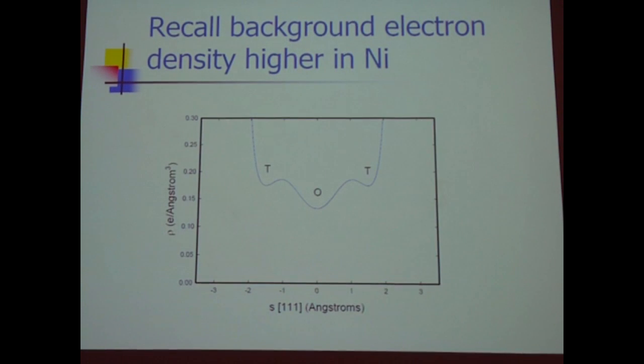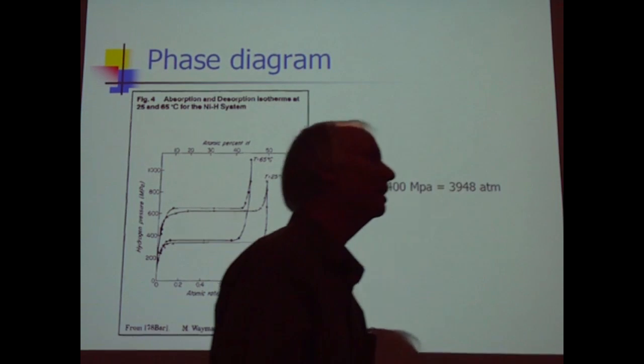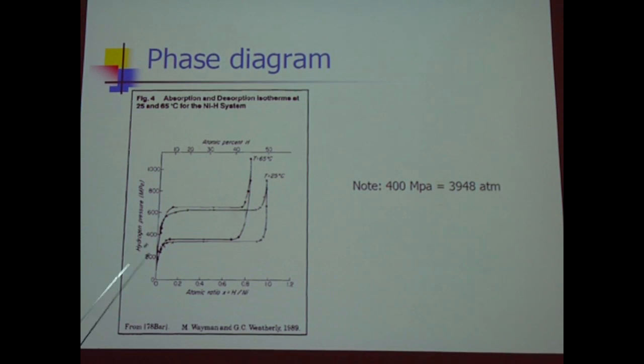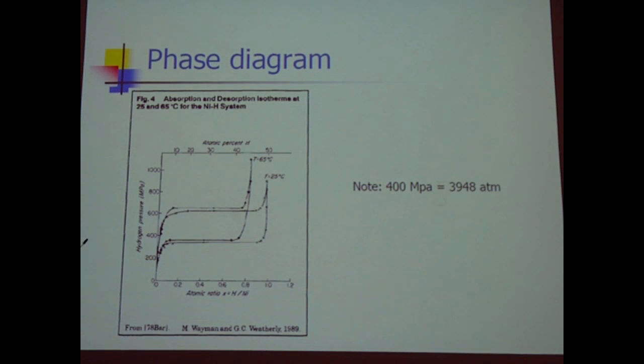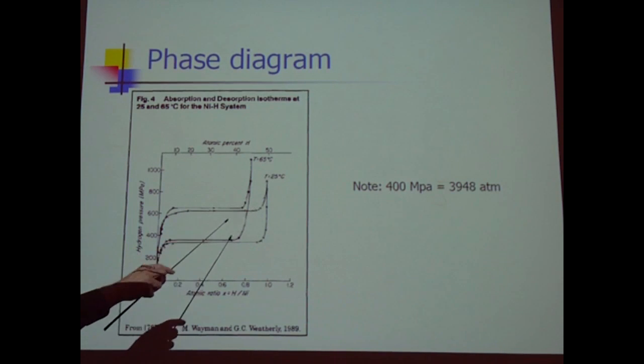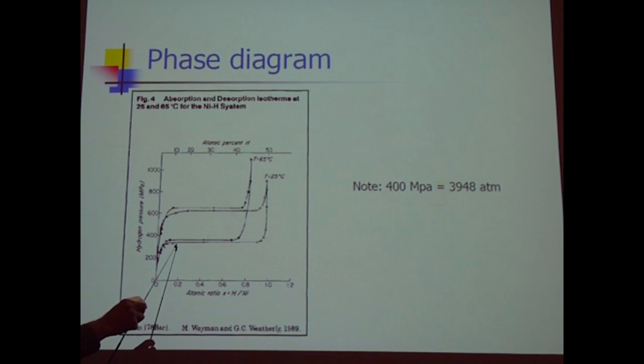So we take our intuition, at some point we go to experiment, and here's the experiment. Now, even this phase diagram sort of looks qualitatively familiar. These are the isotherms, low loading, they go up, the isotherm as a function of pressure goes over here, it's flat, there's a miscibility gap, just like there was for palladium hydride, palladium deuteride. The only thing is that this is 25C, somewhere near room temperature in January in Massachusetts.